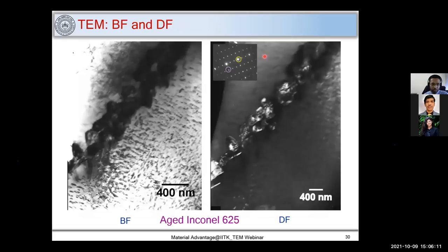Now what is the utility of bright field and dark field? So here there are precipitates which are present, and I get a diffraction pattern. I put an aperture here and I can find out what the precipitates are. So I can clearly identify precipitates just by imaging, or putting an aperture at an appropriate diffracted spot. So it's an application of bright field and dark field.